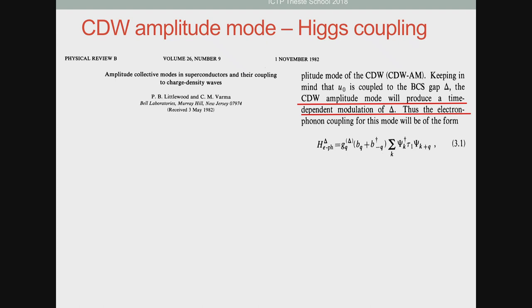The way it is coupled was presumably thought to be that this distortion, by distorting the lattice, modulates the density of states at the Fermi energy, and by modifying the density of states at the Fermi energy, it also modifies the gap. But at that time, in this paper, it was really a phenomenological coupling between the two. We produce a time-dependent modulation of delta. Thus, the electron-phonon coupling for this mode will be of the form, and you see they propose this coupling. So G is really a phenomenological coupling between this operator, which are the bosonic operators of this charge density wave phonon, and the BCS gap function.